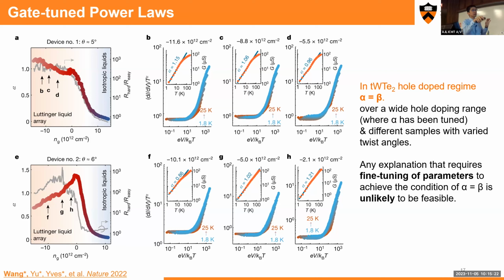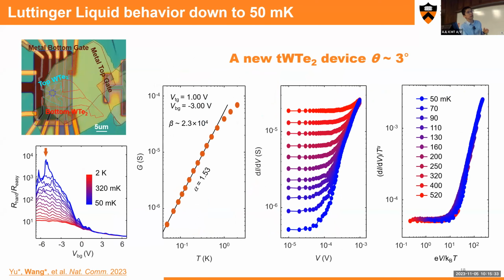But what it shows is that for 5 degrees, the power law behavior shows up at a higher temperature, around 30 Kelvin, while for 3 degrees the power law behavior starts at around 500 millikelvin. So it's around 2 orders lower. There should be a phase diagram if you plot along the twist angle as well as the temperature, but we need to fabricate more devices and work more, and then conclude. Yeah, thank you.